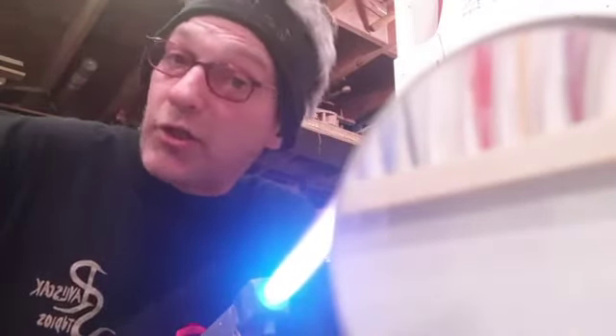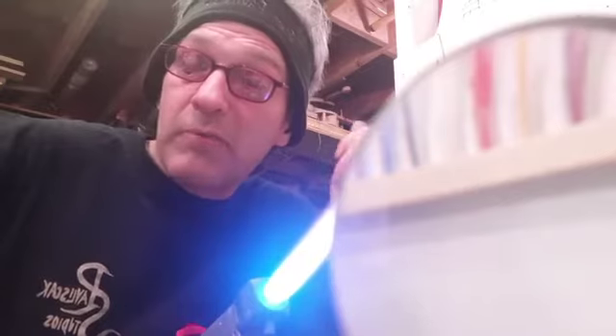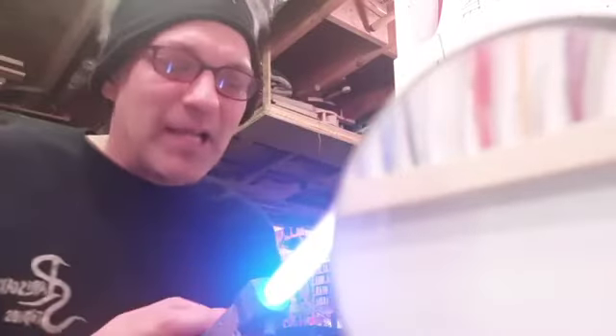Then I ramp down the temperature over a period of another 2 hours, and then turn it off once it gets down to about 500. And then tomorrow, you come out and you look at your marbles. It's a magical experience. And I got to tell you, that never gets old.